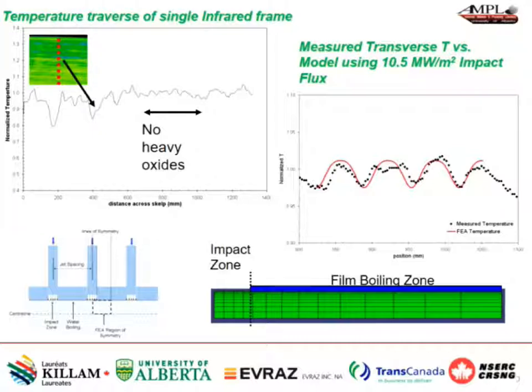So to find the right heat transfer coefficient that will match these variations, we modeled the region of the columns of water that were falling onto the strip, and the strip here is coming at you, and so this is the strip width in this direction. So you can take a certain portion of this where you have the water falling down in a column, you have an impact zone, and then you have the rest of it, which is essentially a film boiling zone. We do a discretization of that regime, and essentially this is well established in the literature.